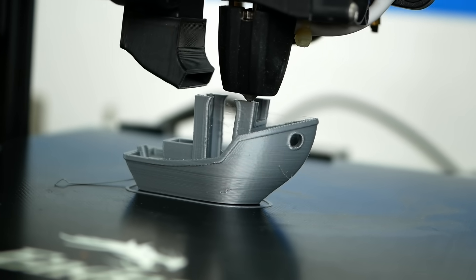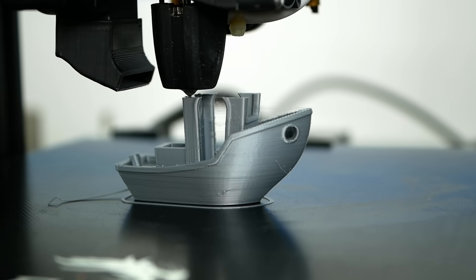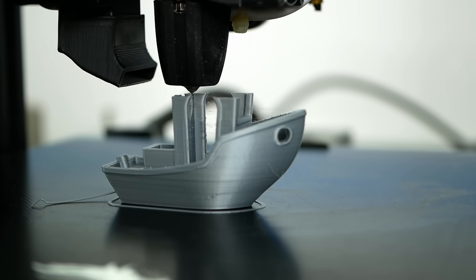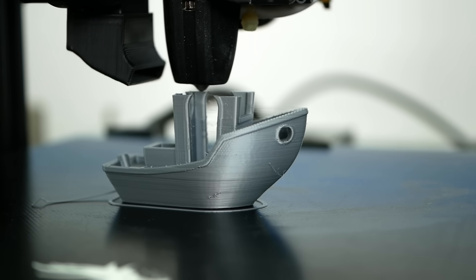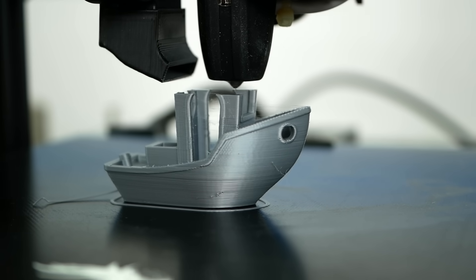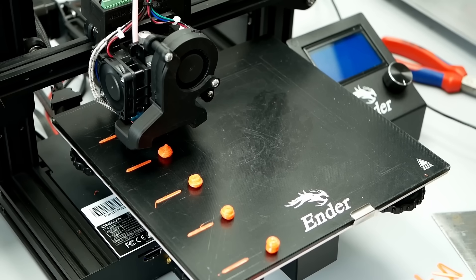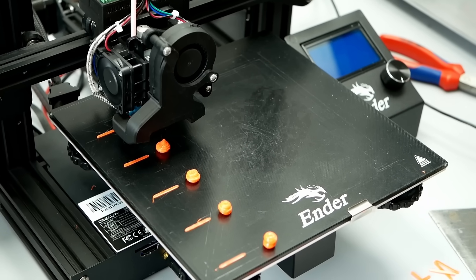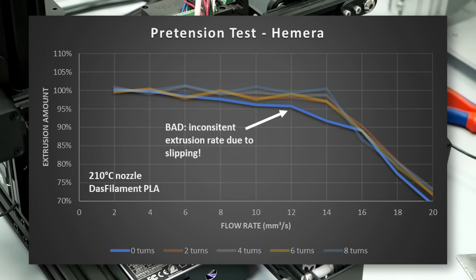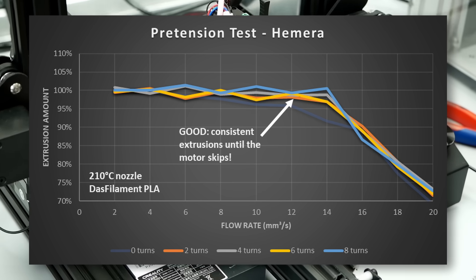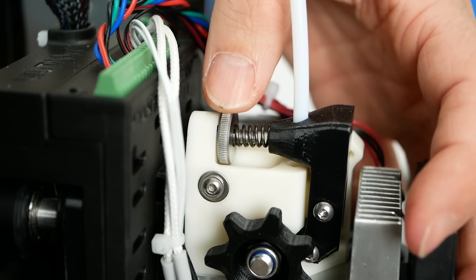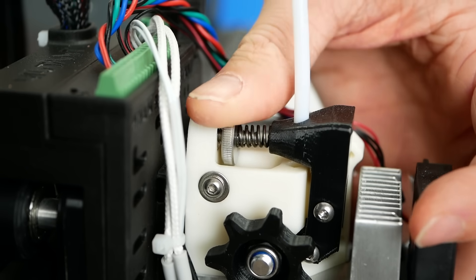In terms of printing quality, you want a feeding force as constant as possible. This means that too little pretension is bad because that can make the filament grind. When it's too high, you severely deform the material which can make extrusions inconsistent, waste energy of the feeder and cause skipping. You can either find your sweet spot with a bit of trial and error or by doing some extrusion tests where you're looking for a pretension setting that gives you very consistent results over a broad range of flows.